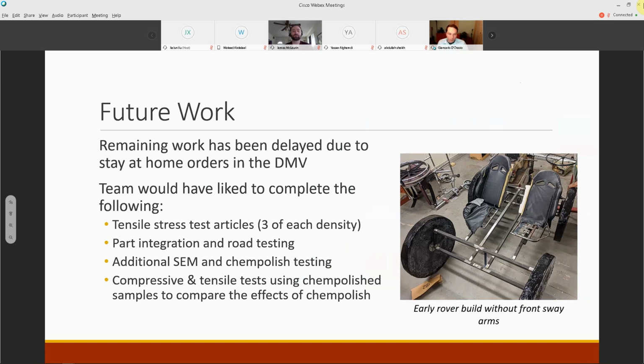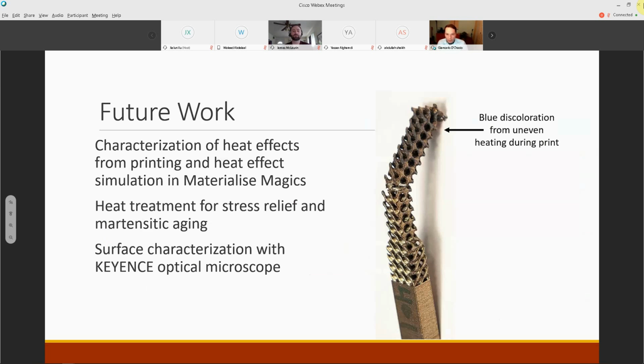We would also like to do additional SEM work and chem polish testing, so testing the samples that have been chem polished versus the ones that haven't. And we also have some other things further along the line: characterizing the heat effects of the printing, heat effect simulation, and Materialise Magics. So that's the software we use to actually make these prints slice for the printer. You can see in that picture to the right, there's some bluish discoloration at the top of the part, and that's due to the uneven heating during printing.